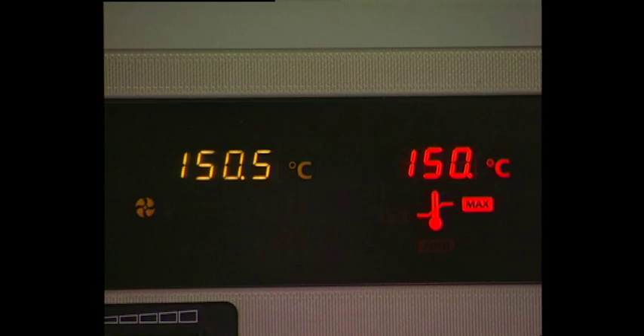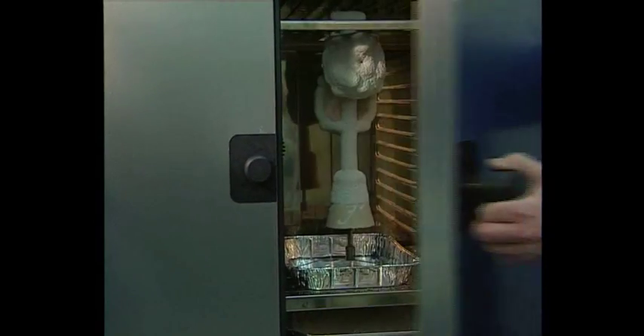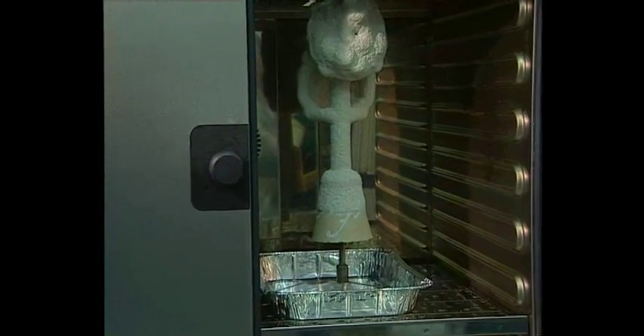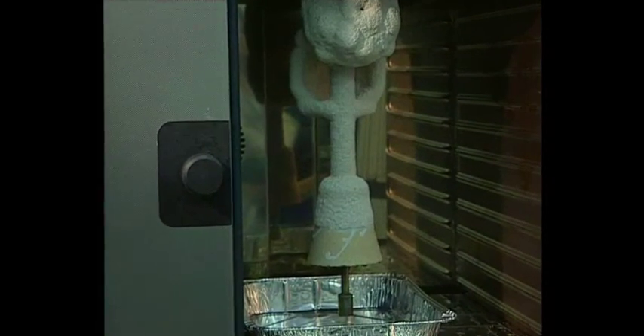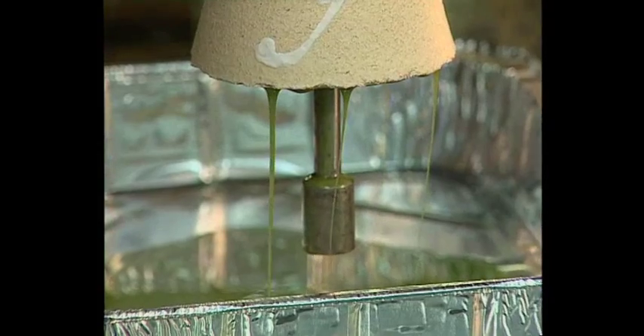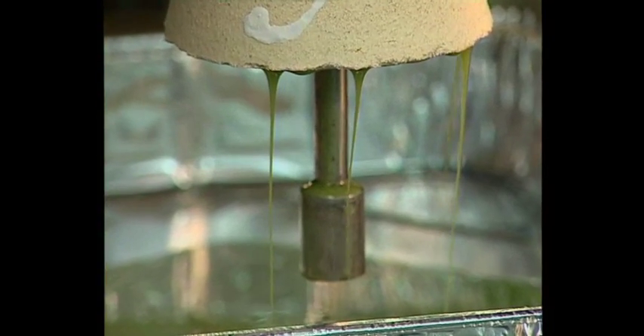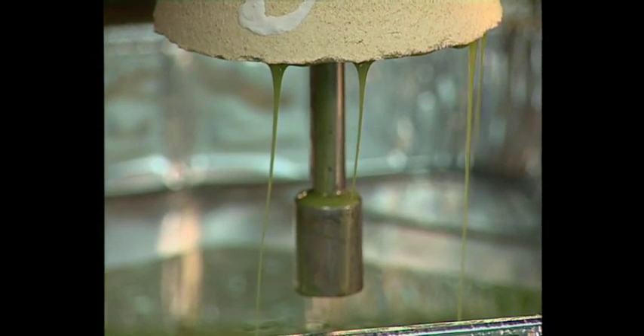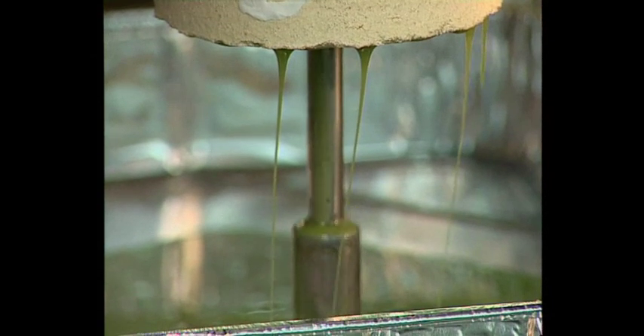As soon as the last layer has dried, the tree can be melted out in the oven, which has been preheated to 150 degrees Celsius. This procedure takes around 40 minutes, and it's so remarkable because the expansion of the wax would have cracked a conventionally built shell. Due to a 50 percent higher strength, the shell produced by the cyclone technology in this process can be finished without any risk of the shell cracking.